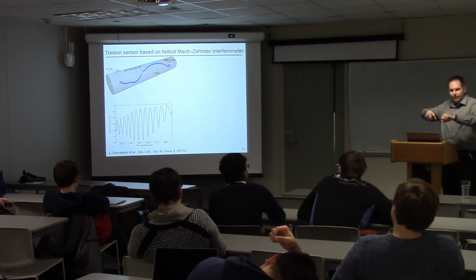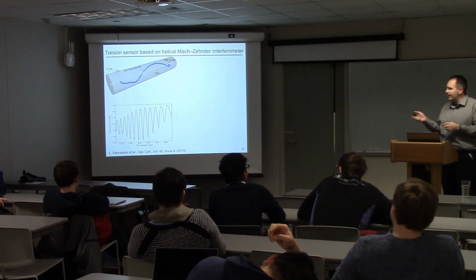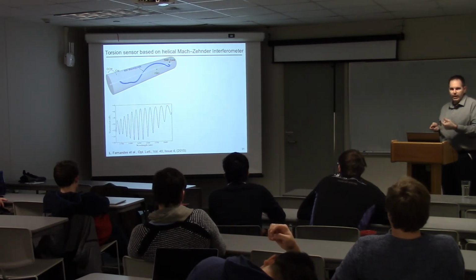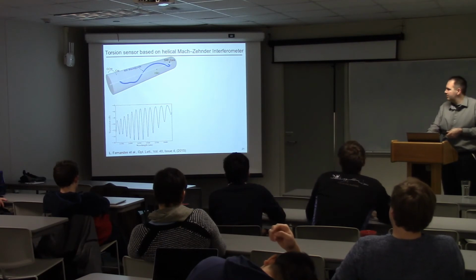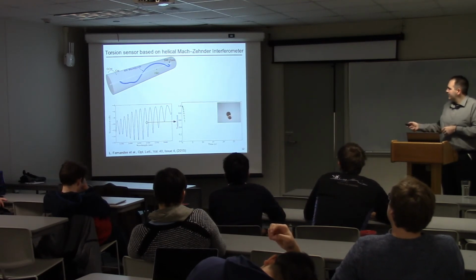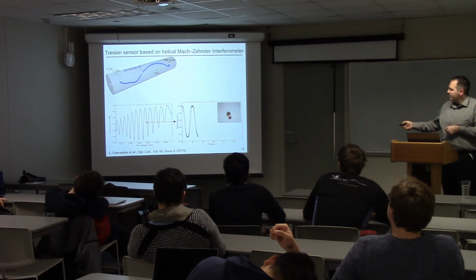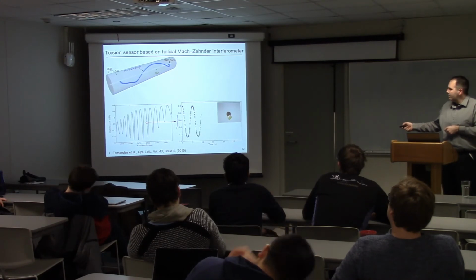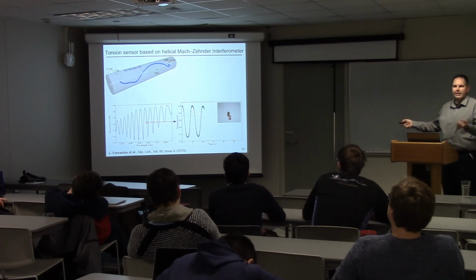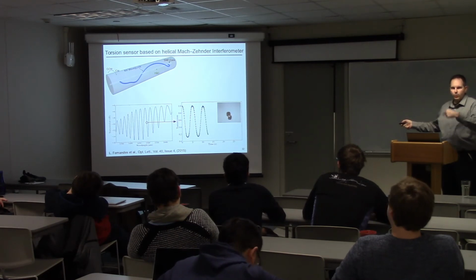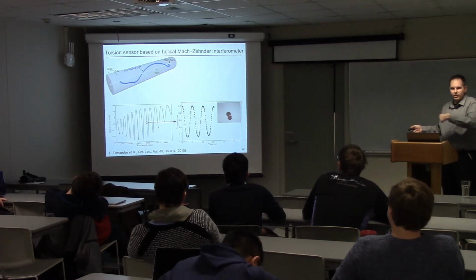And if you reverse the direction of that, you'll stretch that one. And so the optical path length difference between these two devices changes. And so we decided to make an experiment with that. So we have a piece of fiber that's held here, kind of like a pendulum, and we spun this. And you can see when it spins, if we look at one wavelength, we see the intensity change. So from this plot, you can tell exactly how much torsion force there is. And you can also tell which direction it's been applied, because it's either stretching or compressing.